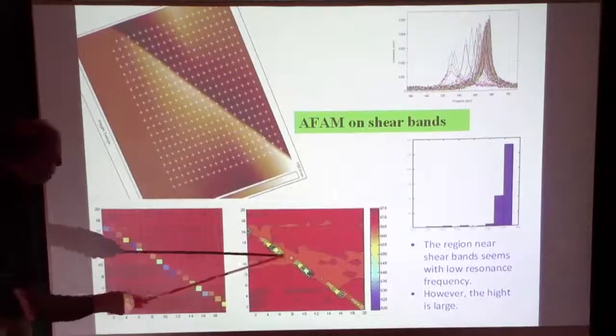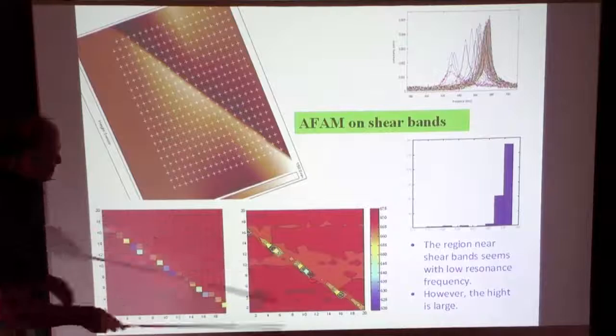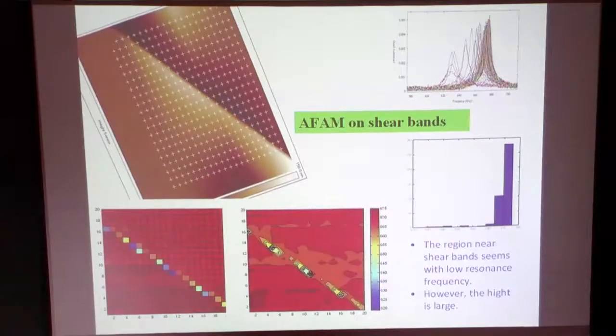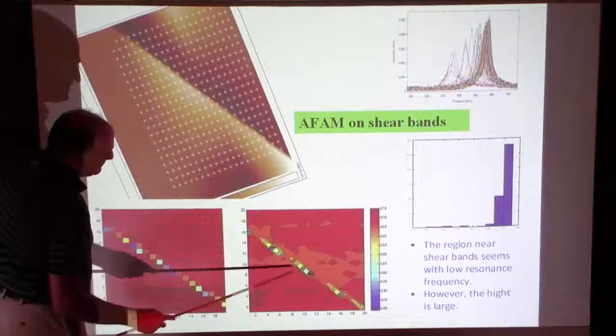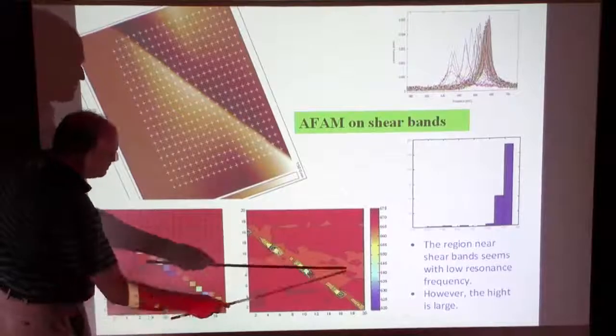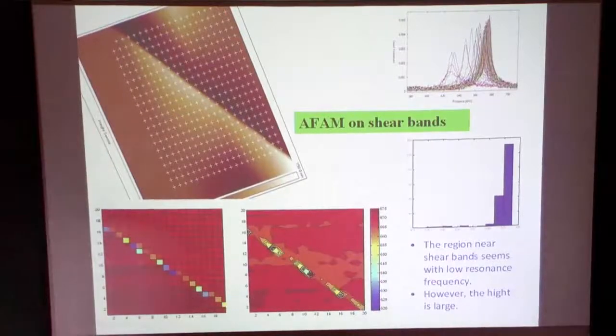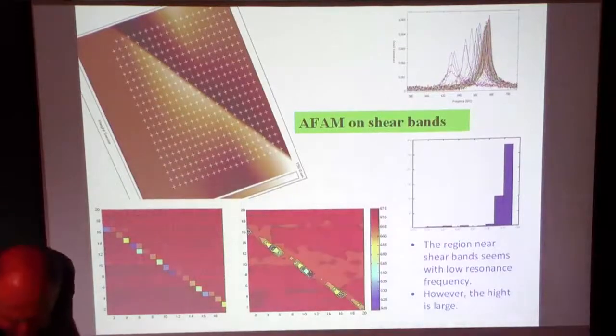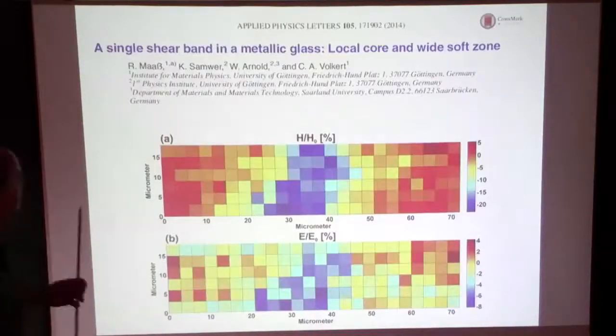Okay, here is a very soft region. Actually, there are regions behind it. It's very clear, the shear band localizes. It is a domino kind of thing. If one tilts, the next one of the meta-basin, you're coming down here. In this area, you go through regions which are soft ones under this 45 or so degrees, and you can see also that there is a long-range tail of that.